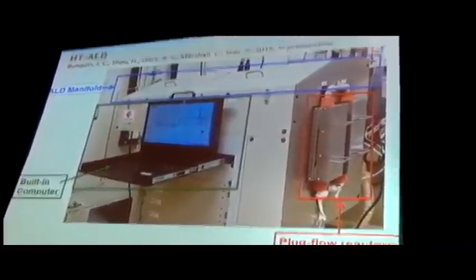But more importantly, the ALD material that we've made here never sees the open air of the laboratory before we actually do the catalytic testing. So we are actually seeing the activity of the catalyst as a function of time on screen.